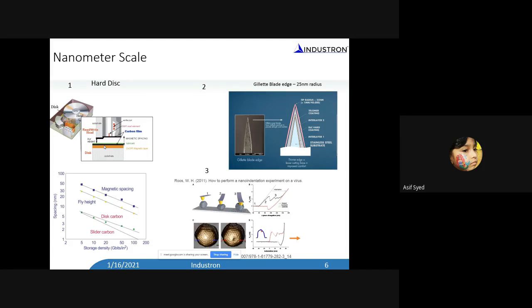Another example that I would like to present is the Gillette shaving blade. Most of you are familiar with this, but probably you don't know. The Gillette blade is a very sharp blade. It's about 25 nanometer tip radius, and it has a coating too. This coating is about 10 nanometers or less. In the earlier time when Gillette was trying to develop this technology, they collaborated with us to evaluate the property of this DLC coating, because we need this diamond-like carbon coating to protect the steel blade underneath. Otherwise, it will become blunt pretty soon.